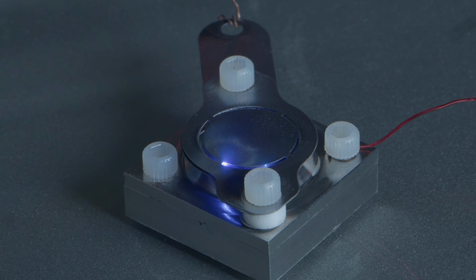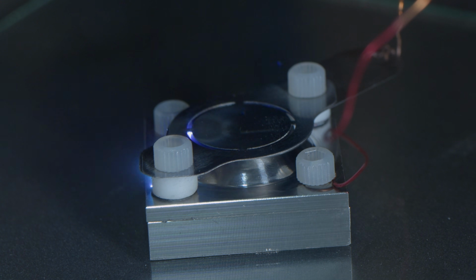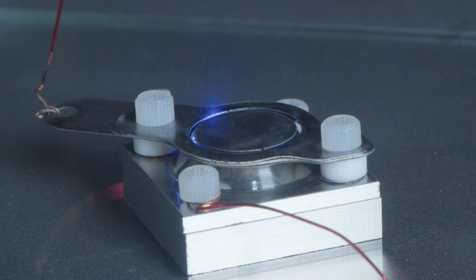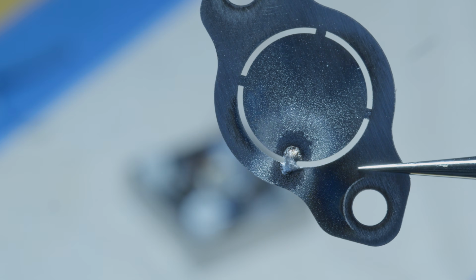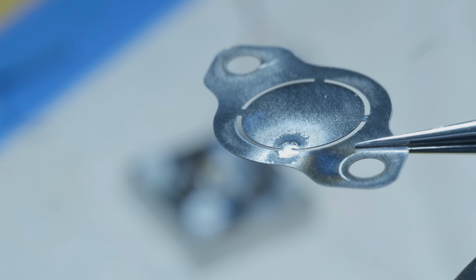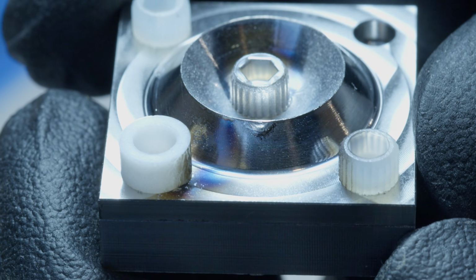The main issue with this design is the bridge section between the inner and the outer electrode. Because it's directly over the slot, the electric field is highest here, and the gallium prefers to emit from that location. It also sometimes spews out droplets, which then connect to the bridge and short the top to the bottom, which effectively ends the test, and you have to vent it all to atmosphere to fix.